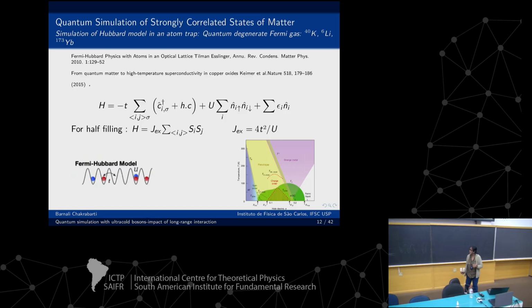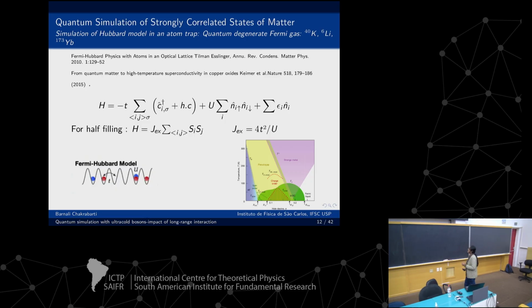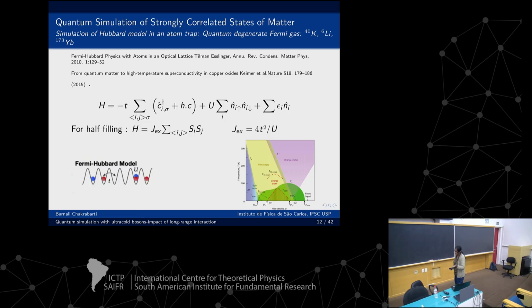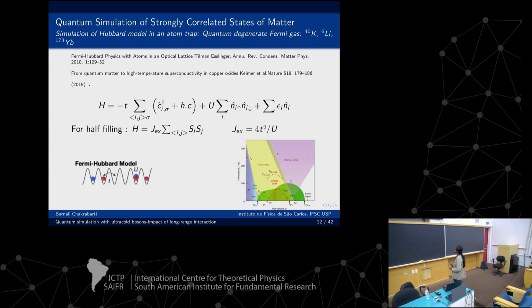Now, if I choose half filling, that means 50% spin up and 50% spin down, then this Hamiltonian reduces to the Heisenberg spin Hamiltonian. This is simply the spin-spin interaction. And if J is the antiferromagnetic exchange interaction, then you have antiferromagnetic order. Now this is an experiment done by the Keimer group in 2015. The material is a cuprate, a high-Tc superconductor, and this is the phase diagram.